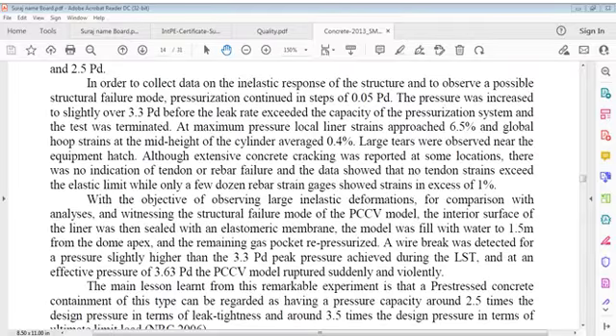With the objective of observing large inelastic deformations, for comparison with analysis, and witnessing the structural failure mode of the PCCV model, the interior surface of the liner was then sealed with an elastomeric membrane. The model was filled with water to 1.5 meters from the dome apex and the remaining gas pocket repressurized. A wire break was detected at a pressure slightly higher than the 3.3 PD peak pressure achieved during the LST, at an effective pressure of 3.63 PD. The PCCV model ruptured suddenly and violently.